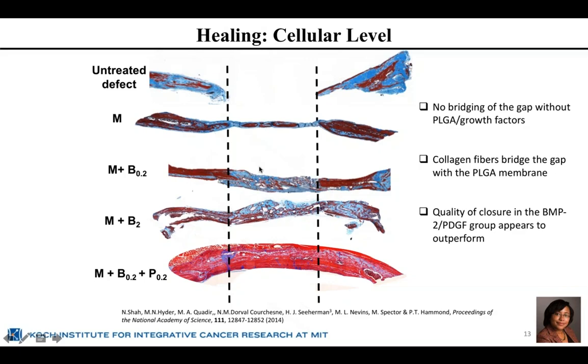It turns out that the mechanical properties of the bone with just BMP2 is actually weaker than that at the margins, both with respect to impact strength and with respect to modulus or stiffness. However, when we introduce PDGF, which supports vascularization, and if you remember from that release curve, PDGF came out over the first 7 days, and BMP2 was released much more slowly over a period of 30 days. In this case, we see that we get a highly vascularized bone, and that the bone that is generated looks very much like the bone at the margins. On top of that, we see that the mechanical properties match the native bone, high impact strength and modulus.